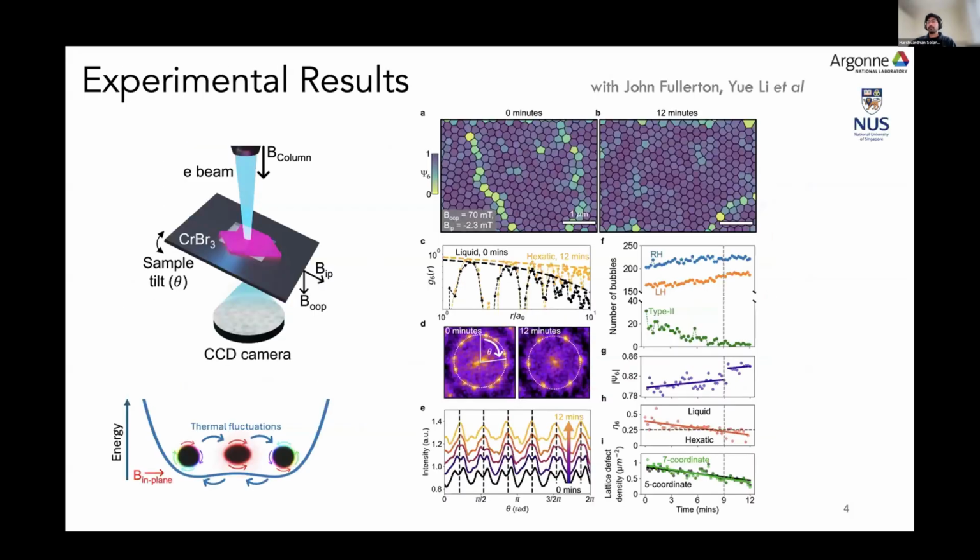So, okay, how does most of this relate practically, right? What is the practical relevance of these simulations? We turn to some remarkable experimental findings where we see that at some critical value of the in-plane field, where the energy barrier between the Bloch states and the type 2 bubbles is generally equal, thermal fluctuations can induce a sort of switching between these three states.